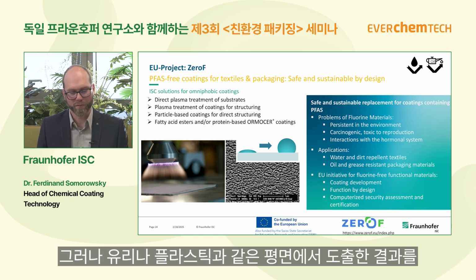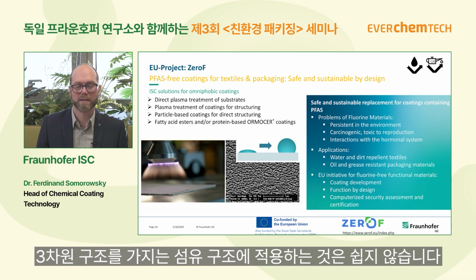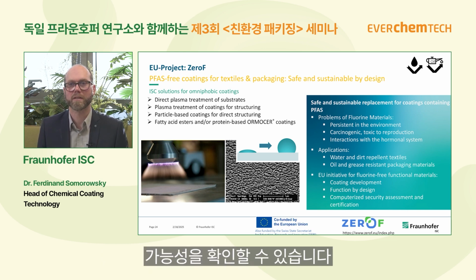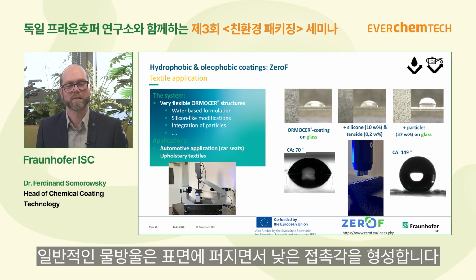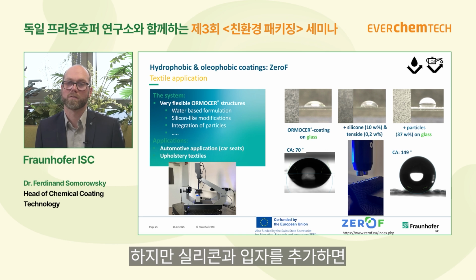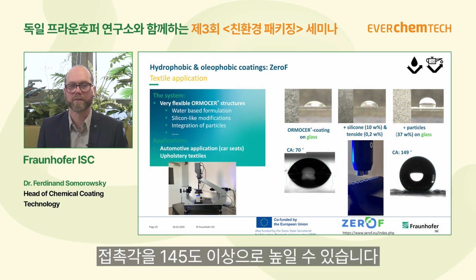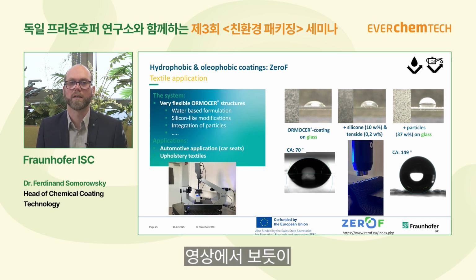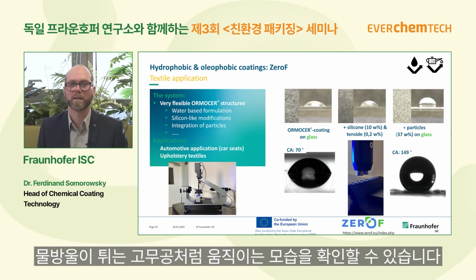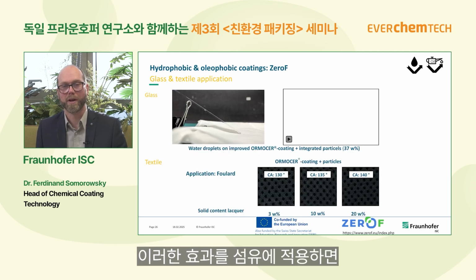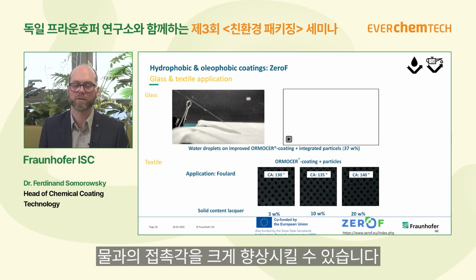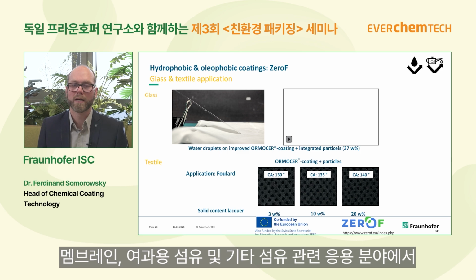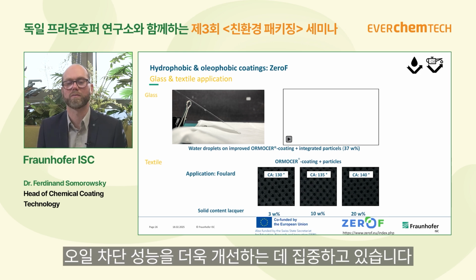It is not very easy to transfer the results from flat surfaces, for example glass or plastic, to the textile structure, because you always have a 3D effect. But what is possible here is shown on these pictures. You see a normal water droplet, it flattens down, so you have a low contact angle. But with the silicone, also with the particles, you can form contact angles of more than 145 degrees. And you can see in this video droplets that behave like gummy balls, and when you transfer it to textiles, you can also achieve very high contact angles towards water. At the moment the task is to also improve the oil repellency for several use cases, especially for membranes or other textile applications, filtration, things like that.